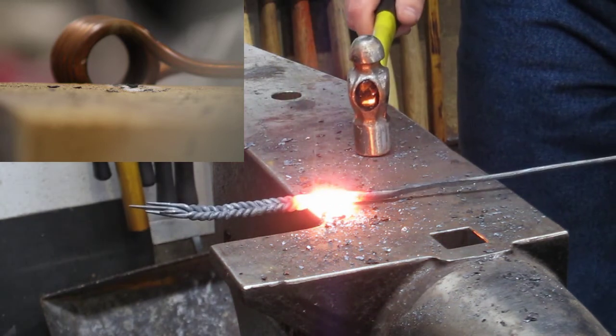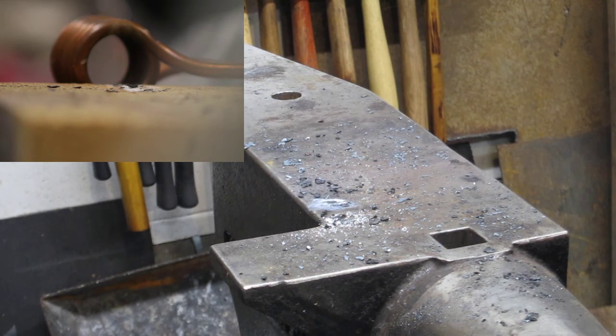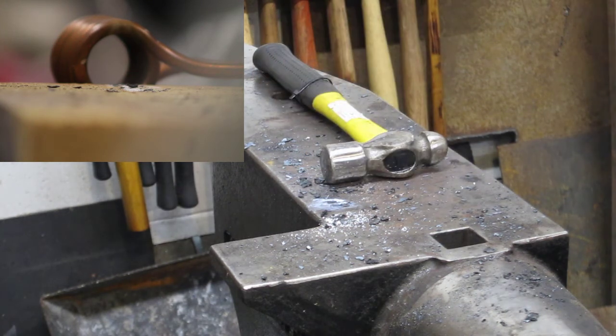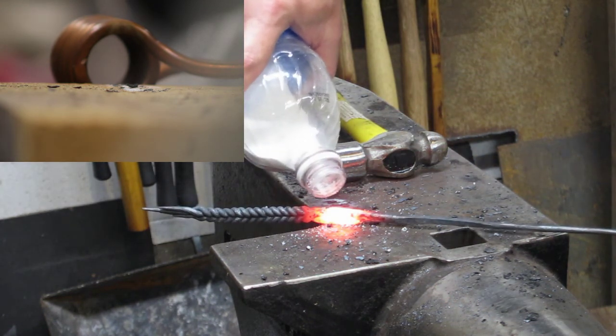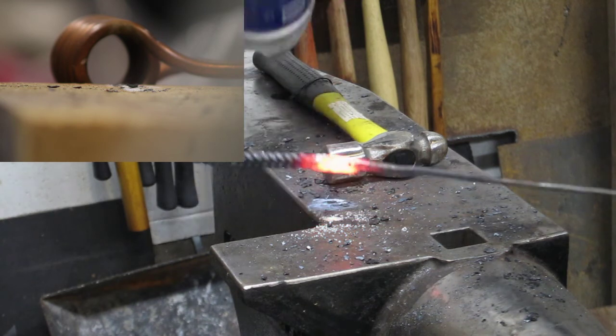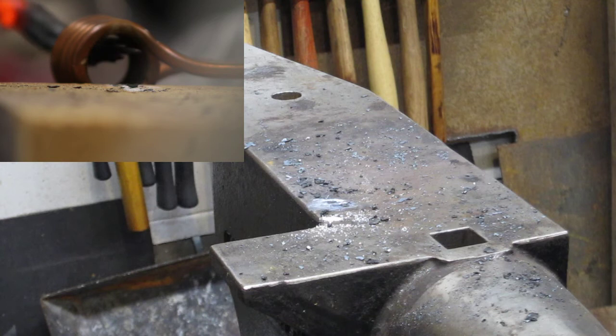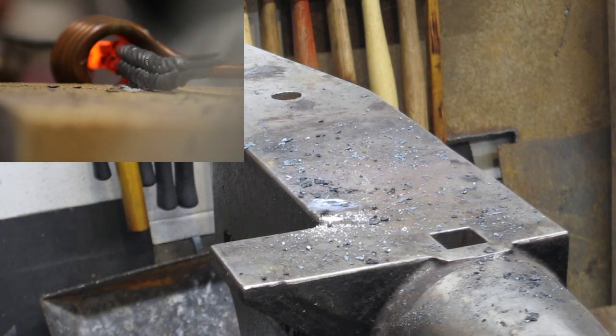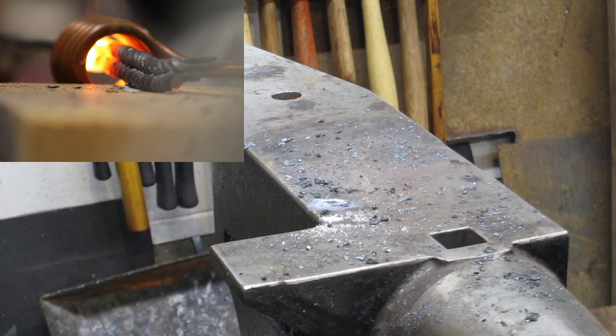So it's all looking good, everything's coming together, the weld is taking, I'm getting everything to join and blend. I'm going to get one little bit to blend right here so I'm getting some flux on it. That way they don't have to quite be as even a heat. The flux will get the scale to melt to the lower temperature and I can get fusion. So that little piece that I'm having trouble getting to heat, hopefully the flux will take care of it.